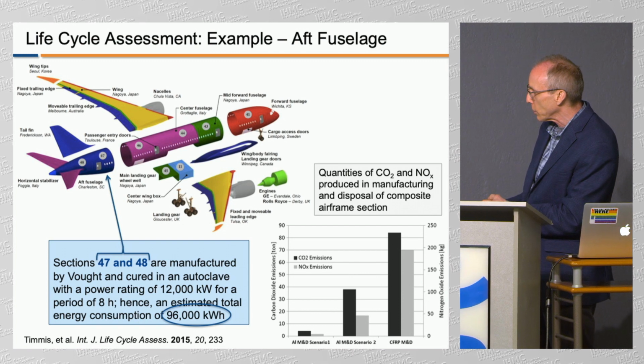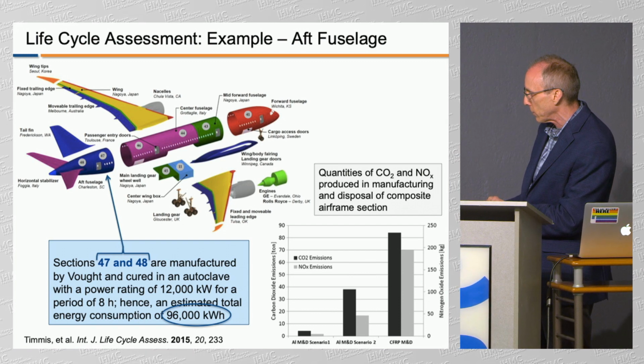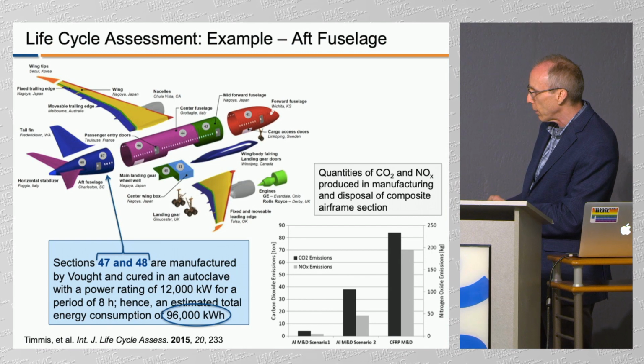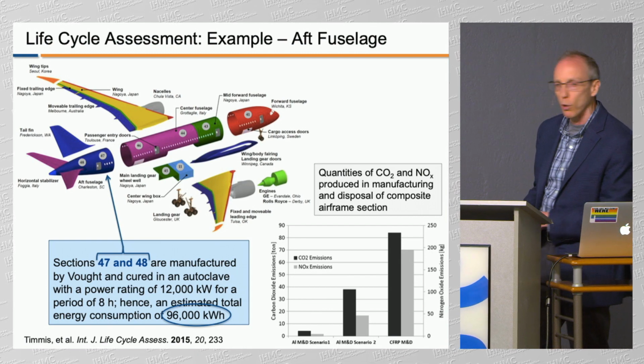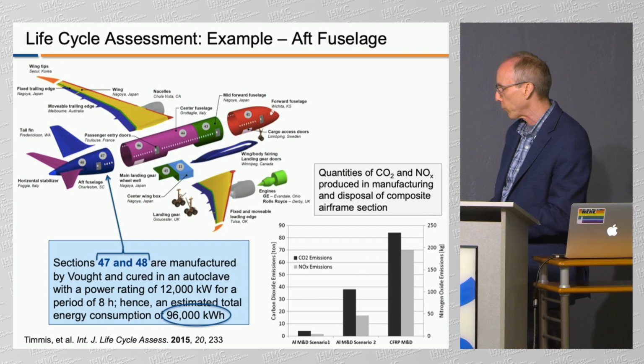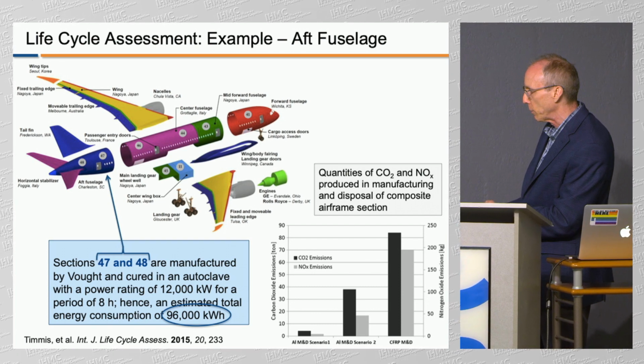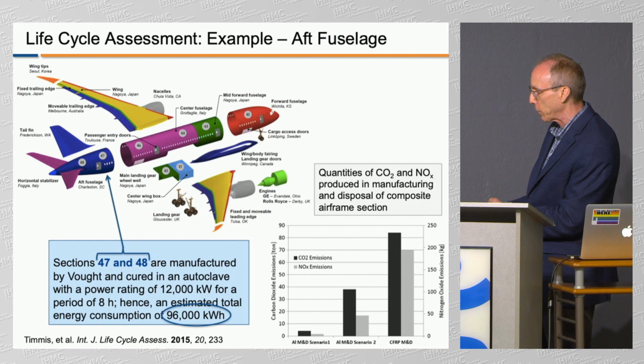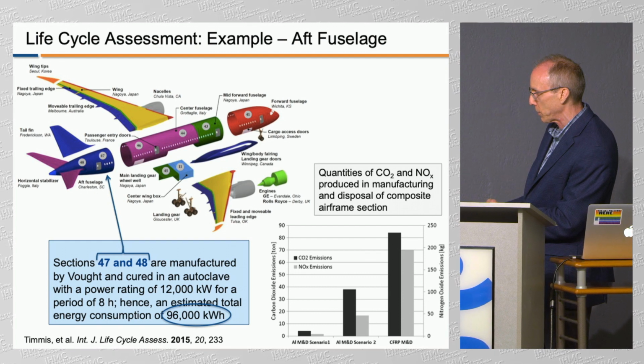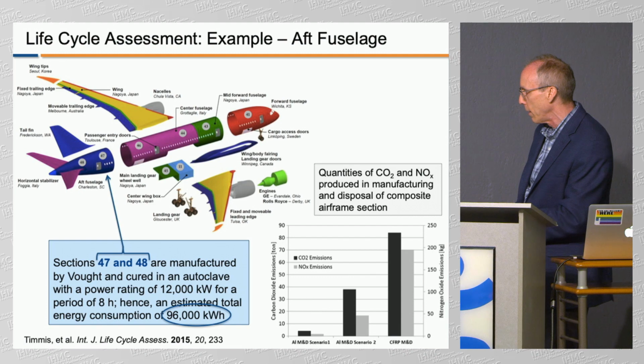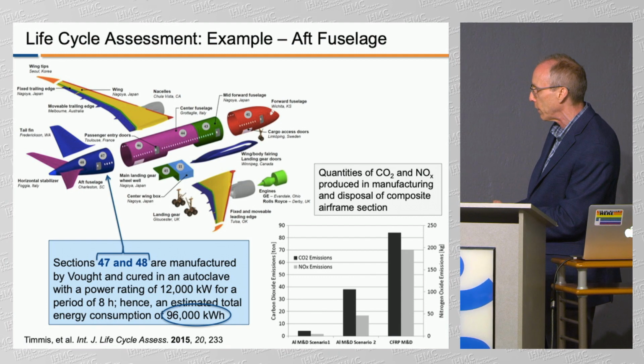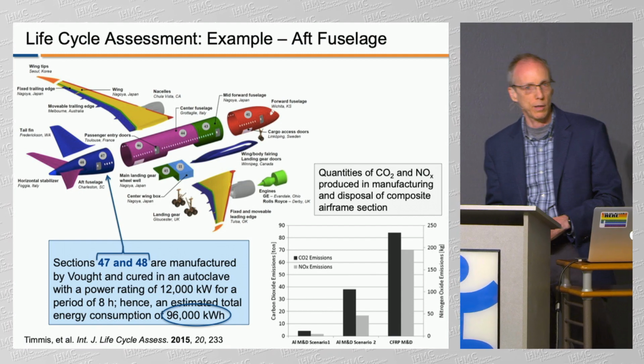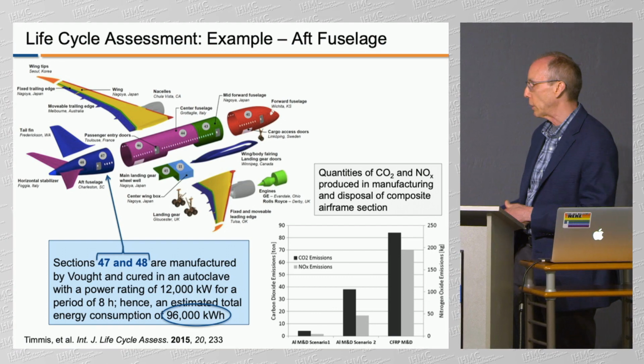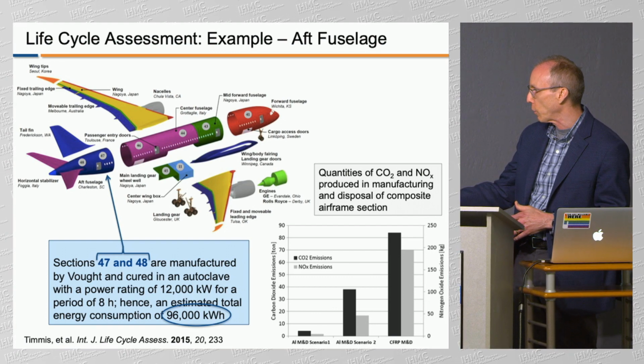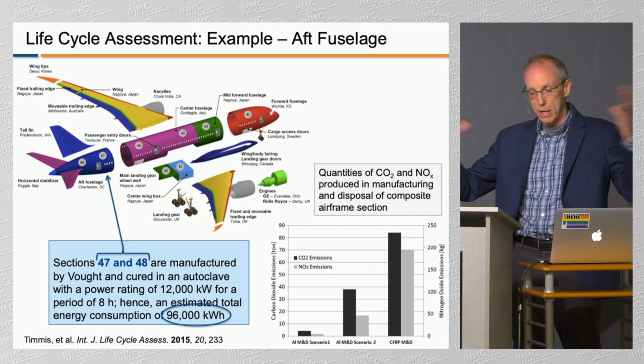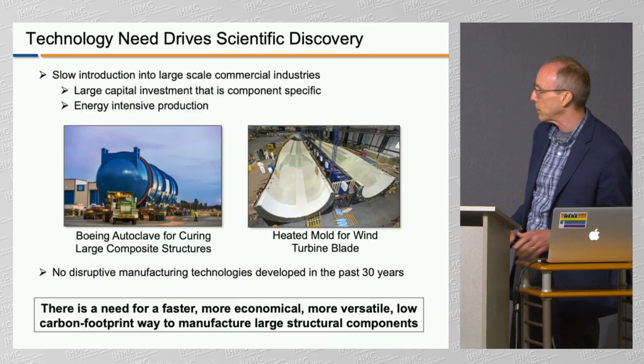Carbon dioxide emissions, that's the black bars. We'll just pay attention to that. Very low footprint, very little energy for aluminum manufacture and disposal. This is another scenario where the aluminum is actually not recycled. In this case, the aluminum is recycled, so you can see it has a lower footprint. But you can see a much higher carbon footprint for the carbon fiber composite material. And it's largely due to this 8 hours of curing at 180 degrees Celsius in a huge autoclave, which you can see on the next slide.